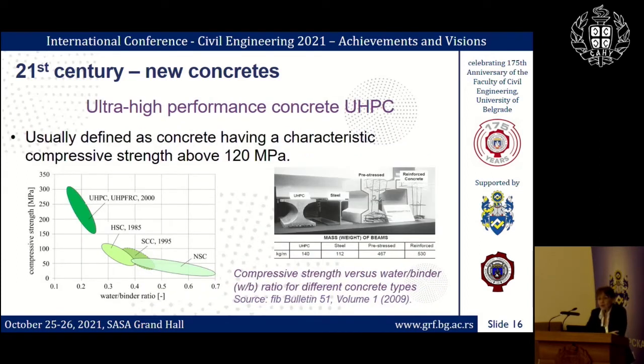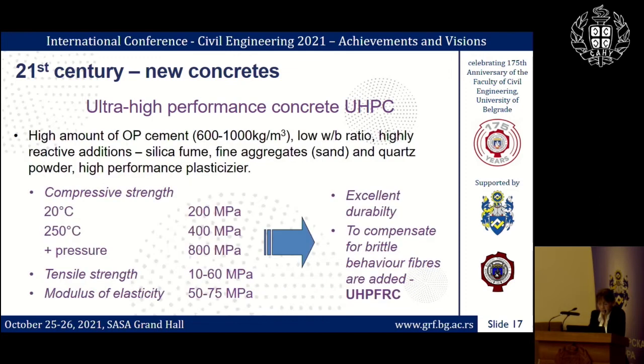Another new type of concrete which was developed in the 21st century is so-called ultra-high performance concrete. Invention of plasticizers and super plasticizers enabled us to produce concrete with the compressive strength which is higher than 50 to 60 megapascals, which was in fact the upper limit for, let's say, ordinary normal strength concrete. Since 1980s, first high strength concrete was developed with the strengths up to 100, 120 megapascals. And since 2000, we now have developed concretes with very high strength, which, as you will see, can be up to 800 megapascals.